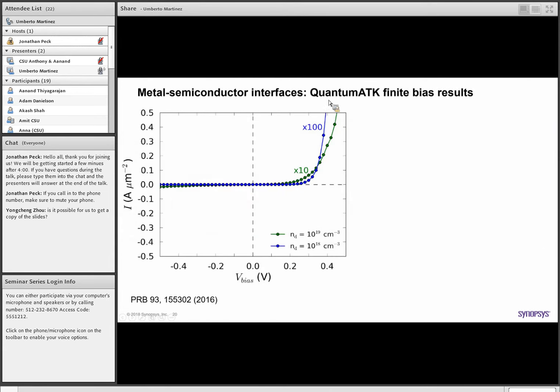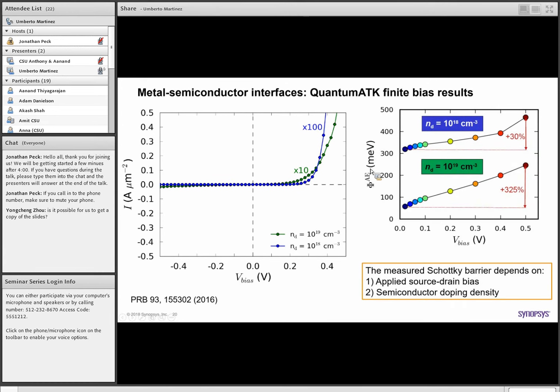The next step will then be to apply a bias. So this is a typical result. This is an IV curve. So you see the current as a function of the applied bias, from the applied bias on the source and drain. And the curves are for two different doping densities. From this picture, we can then do a lot of analysis, and the analysis that I show here is how we can calculate the Schottky barrier as a function of the bias and as a function of the doping densities. All the details are reported in this reference.